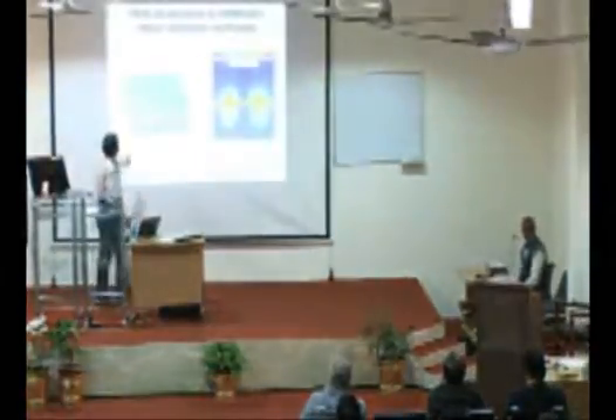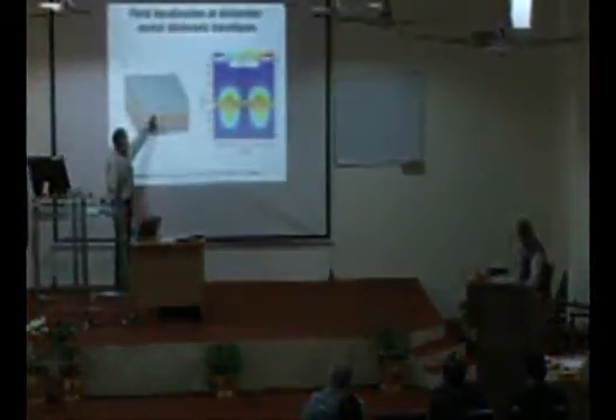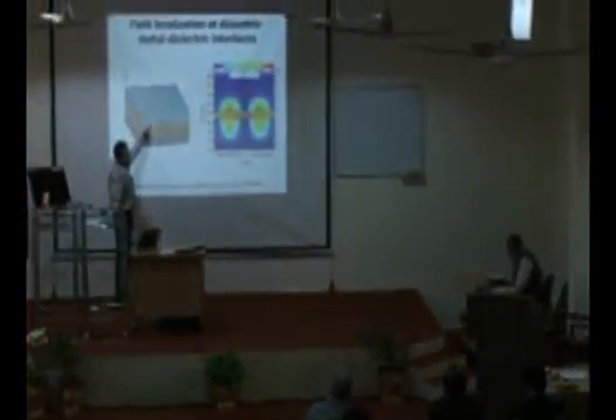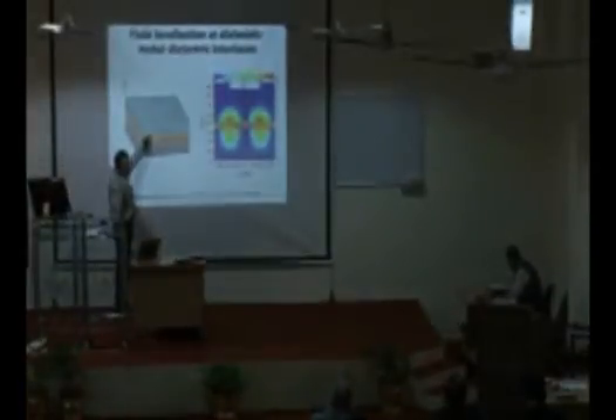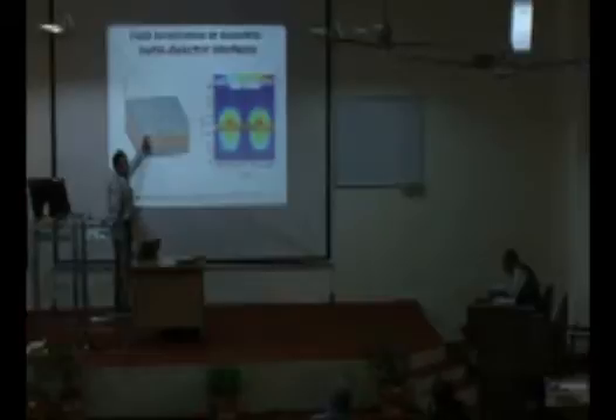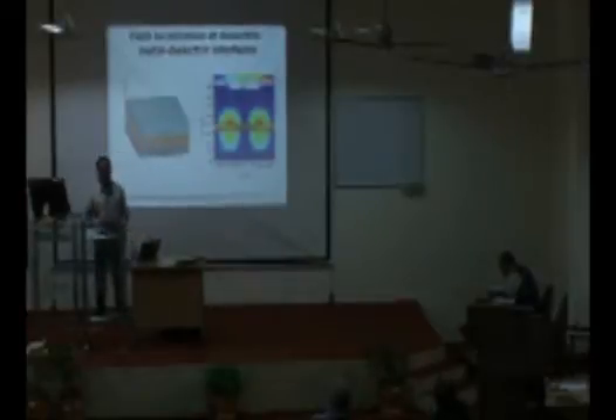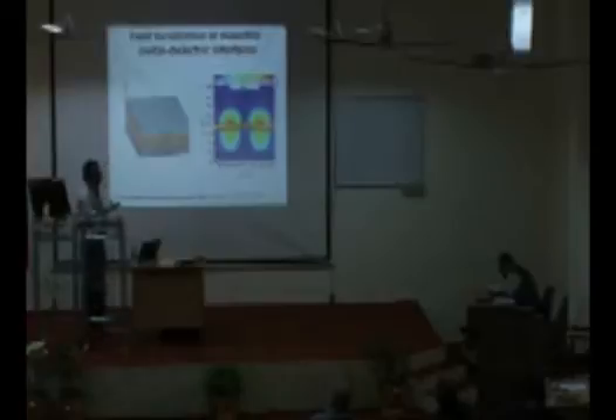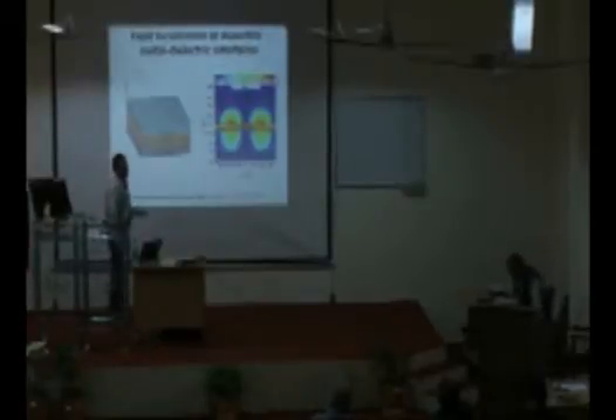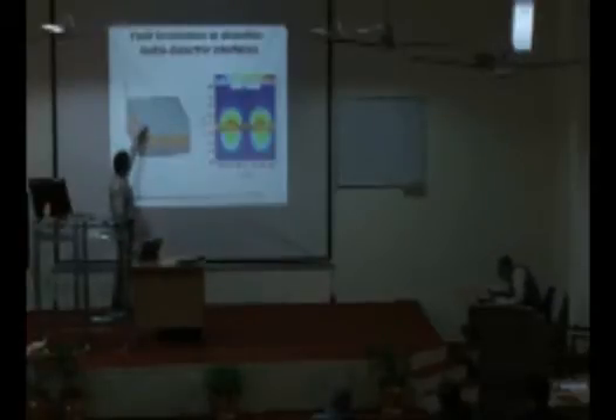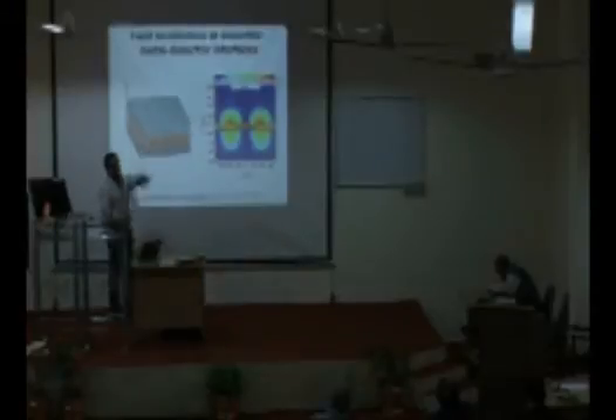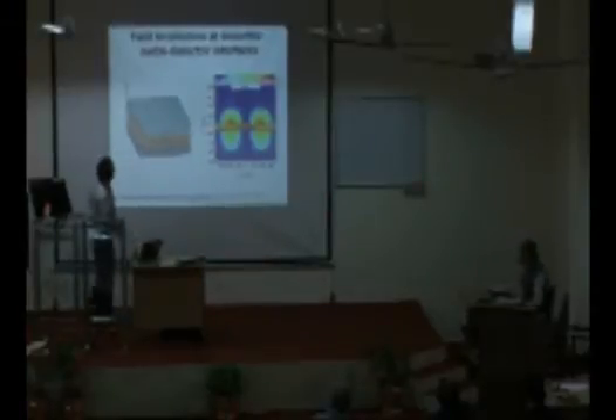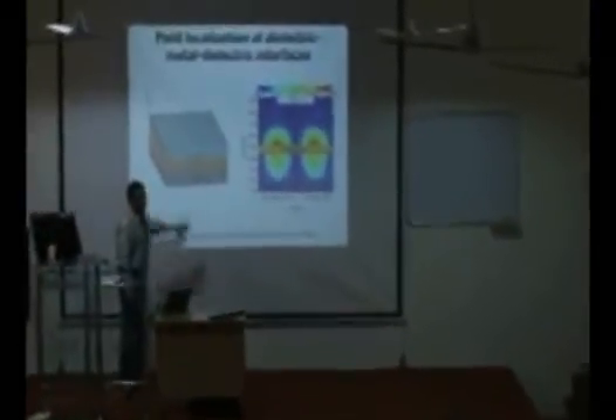The idea is this. We want an unpatterned interface here. We can make these holes come till here, but in which case you have a metal layer here, and the metal dielectric interface will be angle dependent again. The resonances will shift a little bit because the interface is different now, and we have actually studied those as well. But here the interest is that this is completely unpatterned. The pattern is only here, which modulates the incoming light. The way to understand it is that you have the plane wave incident, the reflected component modulates the incoming light, and so you have specific components which couple into the surface mode.